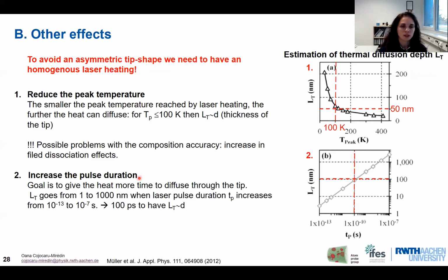Now there is a second strategy, which is to increase the pulse duration. We see nicely how the diffusion length is strongly dependent on the pulse duration. We can increase the diffusion length from 1 to 1000 nanometers simply by increasing the duration of the pulse from 10 to the minus 13 seconds to 10 to the minus 7 seconds. Of course, increasing the pulse duration might also induce some other, non-desirable phenomena, as we have discussed at the beginning of this lecture.